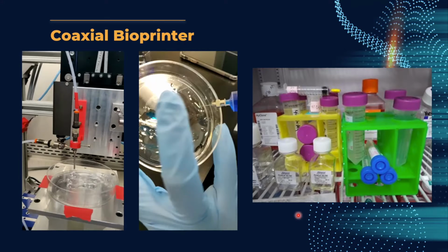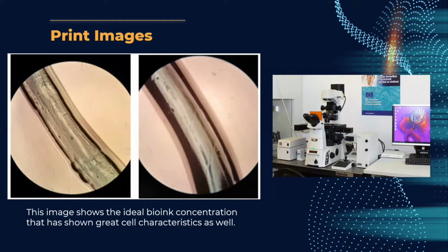These are just some of the materials that we use to create the hydrogel. In our lab, we use calcium chloride, sodium alginate, and collagen, which are our main materials for our gels. And we tested a bunch of different concentrations and combinations of these materials to get that tubular structure. And so moving on, these are some images that were taken with our Nikon fluorescence microscope at our lab.